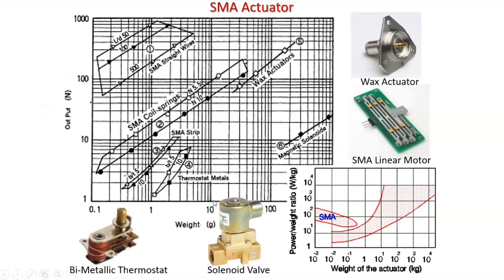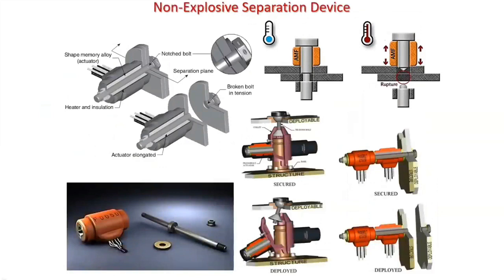And even the strains, we hardly use those 6%. It's only 1% strain that you will finally use. So it's very large, and it's good enough to replace. And as you see gradually in the market, most of the old actuators are being replaced by these. And the advantage of this is these are very compact. And if you see some of those applications, I'll show you how compact they can get to be.